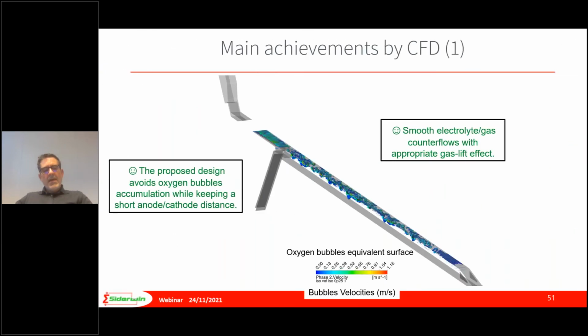So in the next two slides, I will just show you that we were able to address those issues, and we made maybe three main achievements using CFD. What you can see here is that we were able to propose a design that avoids oxygen bubbles to move everywhere in the cell. And we were able to avoid accumulation of bubbles in the cell while keeping a very short distance between the anode and the cathode. We were also able to deal with the electrolyte/gas counterflows. We were able to take advantage of the gas lift effect and to properly deal with the electrolyte/gas counterflows. It was the second achievement.